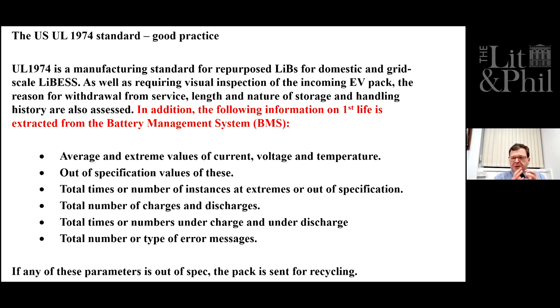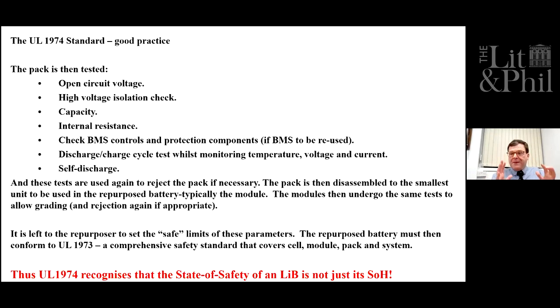First of all, it uses the battery management system information, if it's available, to look at the past life of that battery in the first life, to look at the number of times it's been abused. And if they don't like what they see, the battery is sent straight off for recycling, materials recovery. So if any of these parameters are out of specification, it goes for recycling. If it gets beyond this, then the incoming pack is tested: its open circuit voltage, its internal resistance, which can give an idea of heating effects, etc.